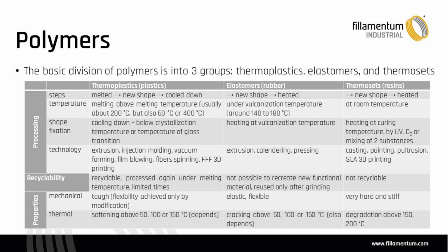Thermoplastics are usually melted, the new shape is created, and to fix it, it needs to be cooled down. They are processed by extrusion, injection molding and also our known FFF 3D printing technology. Elastomers are processed under vulcanization temperature, and to fix the new shape they need to be heated at vulcanization temperature. Thermosets are also processed at lower temperature, and then to fix the new shape they need to be cured by heating, UV in presence of oxygen, or by mixing of two substances. They can also be processed by 3D printing, but in SLA.